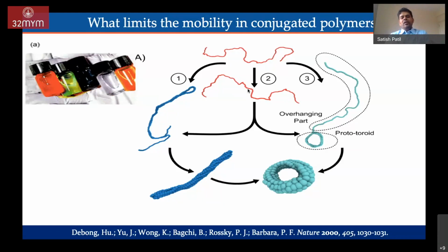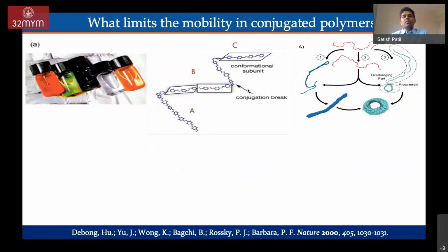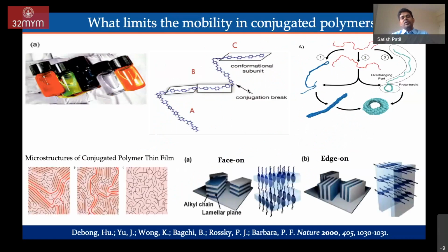So it's a very complex problem to identify what limits the mobility of charge in a conjugated polymer. When you cast a film, in addition to the complexity of the conformation, you do not have any control over the microstructures. A polymer can form, if you look here at my cursor, a range of microstructures, depending upon the kind of environment you provide, the processing conditions, and the annealing temperature at which you make a thin film. For example, a polymer like P3HT can form such well-ordered aggregates.